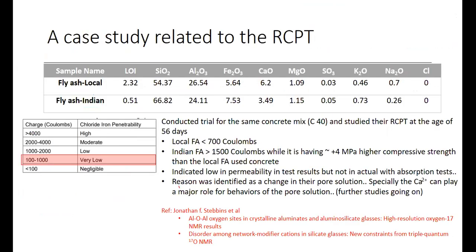Okay, so this is a case study we recently completed related to the RCPT. We took samples of fly ash from our local source and Indian fly ash, and ground them to get much more similar fineness. We produced the same kind of concrete mix design, grade C40 concrete, and studied the RCPT at the age of 56 days. The local fly ash delivered less than 700 coulombs. I will explain what that means.